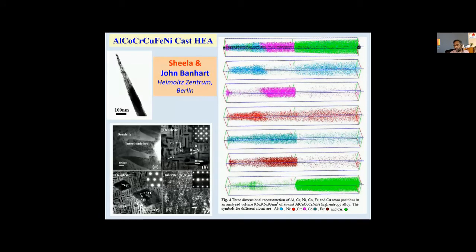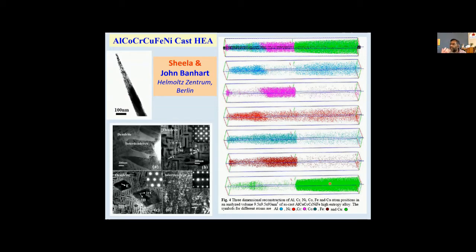In some alloys, for example one containing iron and copper — unfortunately iron and copper are immiscible with each other, they don't like each other for thermodynamic reasons — when you make this cast alloy and put it in the atom probe, you will see that copper completely segregates and iron gets segregated, and this kind of segregation can also be visualized. Atom probe is a wonderful technique for high entropy alloys, particularly to see whether there is uniform distribution of elements or not. By choosing proper elements and proper processing techniques, you will be able to get a uniform composition.